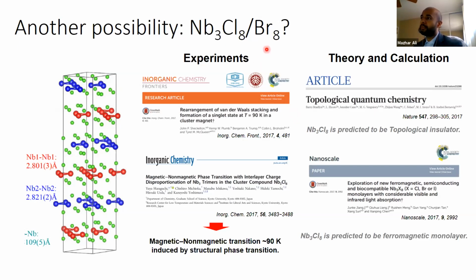So a material that a good friend of mine, Tyrel McQueen, had first investigated over at Johns Hopkins, and now it's two materials, it's a family, niobium-3 chloride and niobium-3 bromide. So they are layered materials. So that's the first checkbox. You can see you have nice layers of niobium in this case, at low temperature, they look to form these little trimers, but an otherwise pretty much hexagonal net stacked on top of each other. Niobium halide layers with a van der Waals gap. So they're really nicely layered and presumably very exfoliatable.